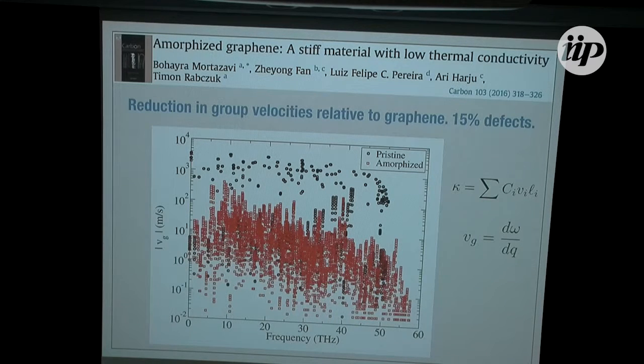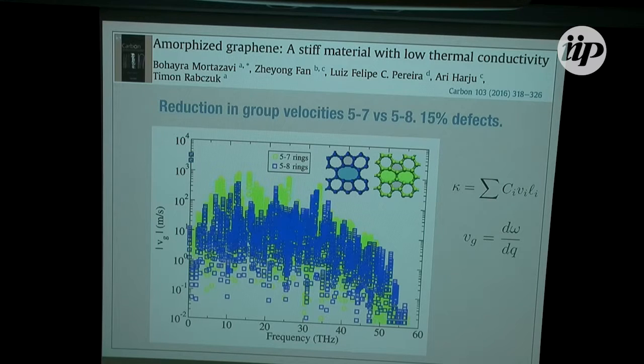Now, the thermoconductivity is also much lower than in graphene, and we tried to figure out why it was much lower. I mean, sure, it's a system full of defects, so the thermoconductivity is going to be lower, but where exactly is the reduction? And we see a severe reduction in the phonon group velocities. So we know that the mean free path is decreasing, but we also show that the group velocities decrease considerably. This is amorphized graphene, and this is pristine graphene. And look, this is a log scale for the phonon frequencies. So the thermoconductivity of defective or amorphized graphene is much lower, not only because of the phonon mean free path, but also because of the phonon group velocities.